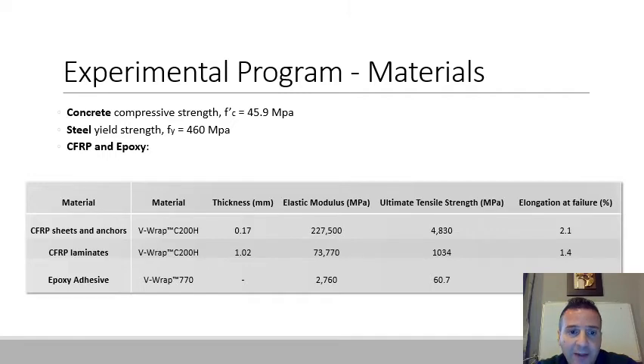The CFRP laminates, with the epoxy, will have a thickness of 1 millimeter. The E will drop, but EA, the elastic stiffness, will stay the same. If you multiply the thickness by the E, it will give you about the same answer, which is about 73 gigapascal. The E and the tensile strength will drop to about 1000 megapascal.